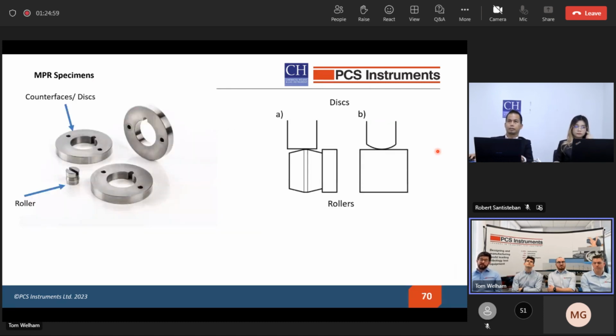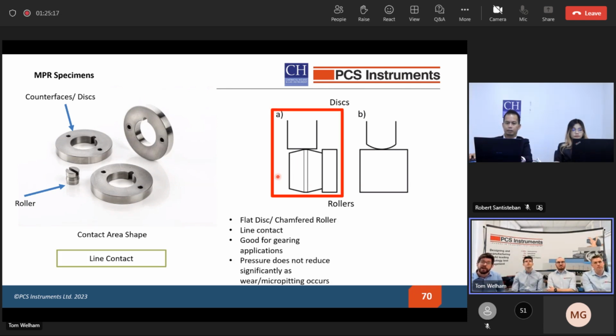I'll talk a little about the specimens that we use on the MPR. As I said earlier, we have 3 counterface discs, and these run against the central roller, and the central roller is what generates the damage. The roller can come in multiple geometries. We can have a chamfered roller, which gives us a line contact. In a chamfered roller setup, we have a flat disc. This is applicable for gearing, where we predominantly see line contacts. And it's very good for generating micro-pitting damage or wear, because as the roller profile is reduced due to material loss, the pressure does not reduce as significantly.